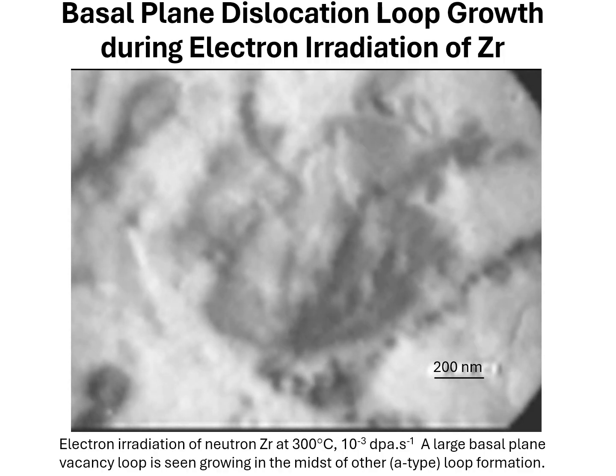And as you can see, it's growing when I irradiate at 300 degrees C, which just tells me in this particular case, because it was a vacancy loop, not an interstitial loop, that my vacancies are mobile under those conditions.